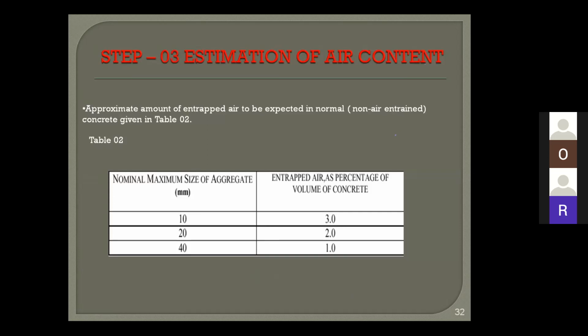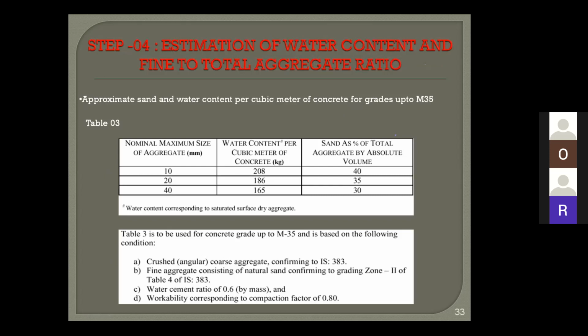And here we are using a maximum aggregate size of 20 mm. So we have to assume that the air content will also be there, 2%. Then in the code book, IS 10262, it was given that the maximum water content we have to use is 186 liters. 186 liters is common. If we are using a maximum aggregate size of 20 mm, 186 liters is the starting value. But by using 186 liters alone, we cannot do the mix design. The water content may be increased depending upon our material properties.